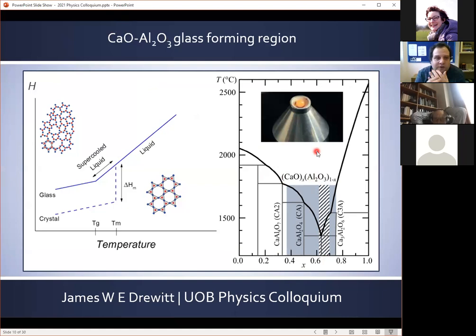We can extend this glass forming region by using containerless techniques, for example, aerodynamic levitation with laser heating. This allows for more rapid quenching, so we can access deeper supercooled states, and it also prevents contamination and avoids heterogeneous nucleation from the sides of any container. And so using this technique, we can significantly enhance our glass forming region. I'm going to concentrate on the equimolar composition here, which I'll refer to as CA, and the calcium-rich end member of this enhanced glass forming region, tricalcium aluminate, or C3A.